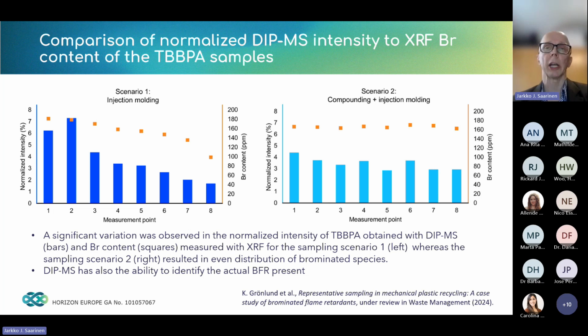If you just want to go on for a direct quantified analysis of the bromine contents, then once you have the XRF well calibrated, then you can go on use that one directly to see how large is the bromine fraction of your species. However, the only thing that you can measure from the XRF is the actual bromine content, but you do not get any additional information about what is the actual brominated flame retardant from which the bromine is originating from. However, if you do the DIP mass spectrometric analytics, then you also have the possibility to see and to identify the actual brominated flame retardant present, as you can see the different peaks, whether it's TBBPA or if it's HBCD or then DecaBDE, for example.